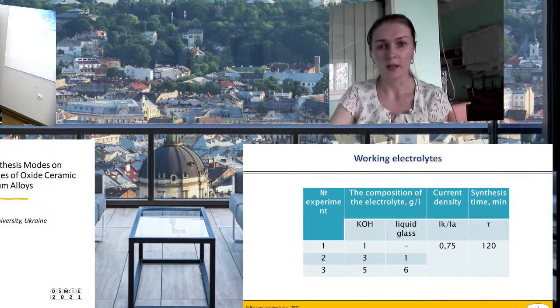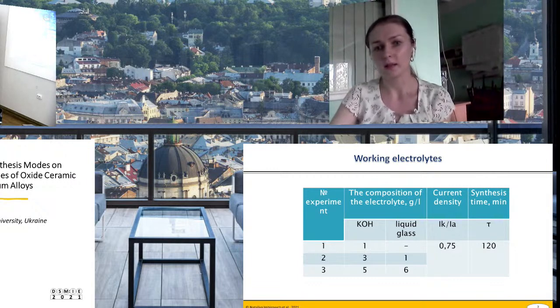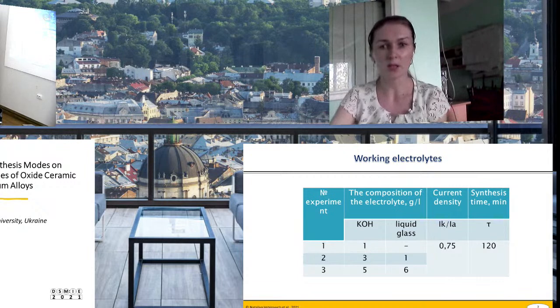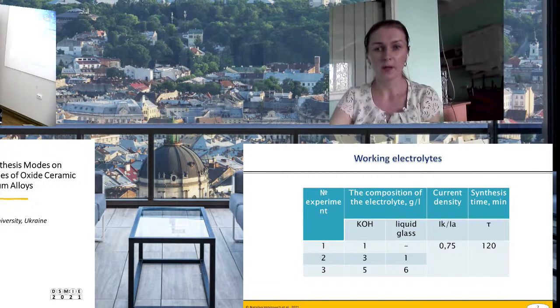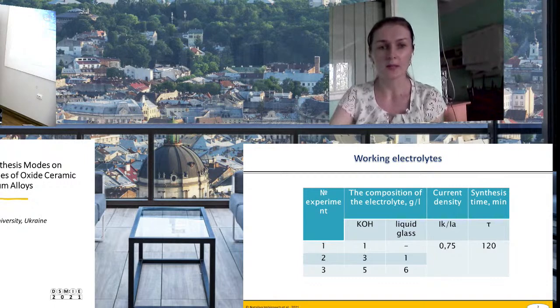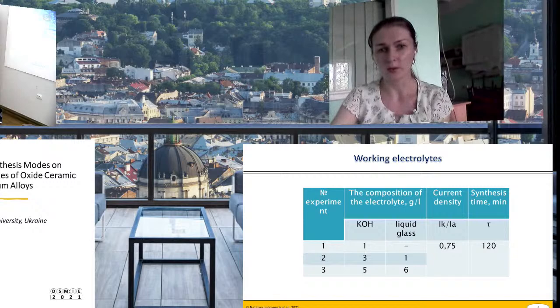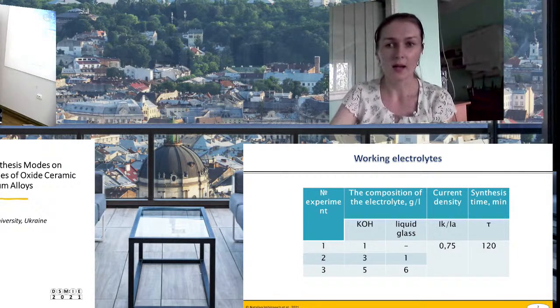Poster 7 gives us detailed information about the experiment, such as the composition of the electrolyte, current density, and synthesis time. As you can see, the experiment was repeated 3 times. It means that 3 test samples were used. This table indicates that current density has a constant value.